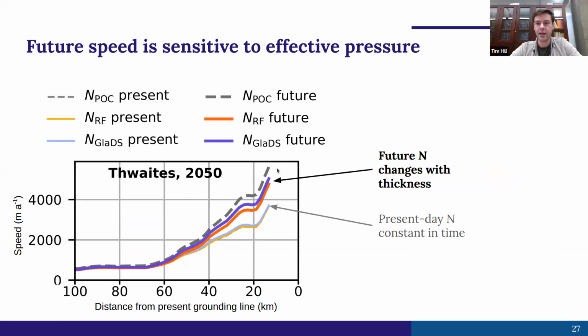The top group, with the darker lines, these 3 darker lines, is where effective pressure changes with ice thickness, which is what you would actually do when running a subglacial drainage model. But in the lighter group on the bottom, we get slower speeds if we don't let effective pressure change in time. So in some ways, this verifies what we know, which is that having active subglacial hydrology or some sort of ice-hydrology coupling is important, because you get faster flow speeds by doing that. What is maybe interesting to point out is that across the different basins we have, this difference in grounding line speed is up to 2,000 meters per year. So it can be very sensitive to how you parameterize effective pressure.